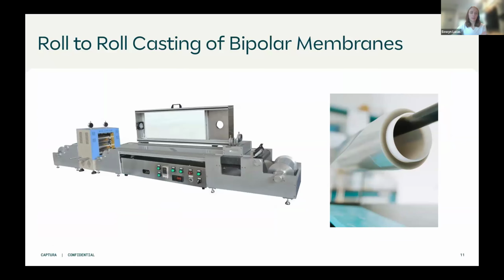This is just a random image, not the exact one that we're working with, but the concept here is that you actually start with a roll on one side of your system. The roll would be some sort of inert backing material. You then roll this through what is typically called a slot die. It's similar to the casting bar, but it actually holds the solution within it. You're able to then extrude the solution onto your backing material as your backer moves through the system. It then runs through the oven and rolls back onto a roll at the end of the system.